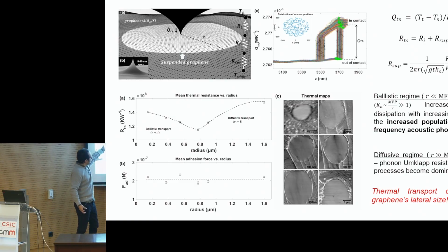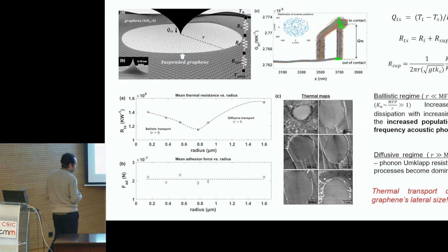And then you see when we pass to diffusive thermal transport, when the radius of our graphene disk is much larger than the phonon mean-free path in graphene, what is happening is that we have phonon-phonon scattering. These are the resistive scattering processes in our lattice, and this scattering increases the thermal resistance that we measure in graphene. And this is the thermal map that we get from this measurement. This is the STHM mapping, so we can see differences, the quality of the graphene, and many other things.